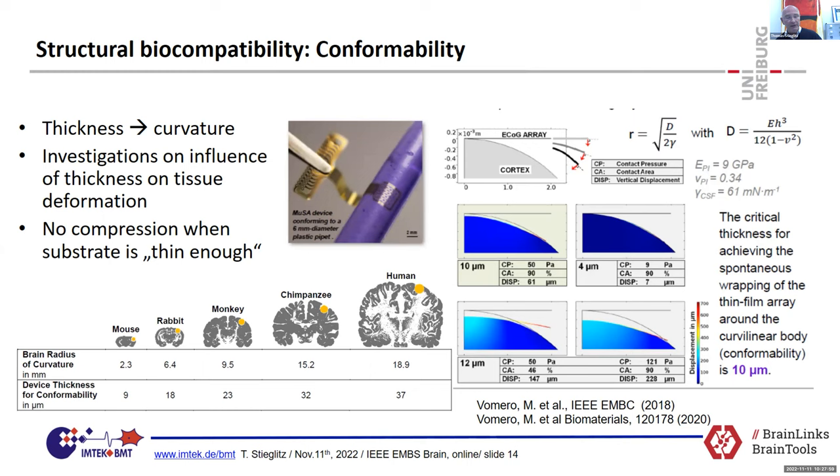The second thing is about flexibility. There's a lot of literature around about flexible materials, and depending on what material you use, you claim that other material is not that flexible. And since some person said our polyimide doesn't work, we thought, well, it works in our hands. What could be wrong with other hands? And we thought we should have a look at the thickness, how thick the material is, how wide it is, and get a kind of conformability measurement based on an adhesion theory model and based on the curvatures that we have in monkeys,